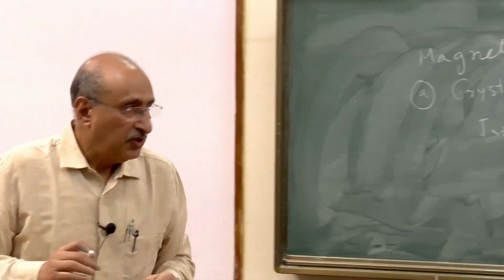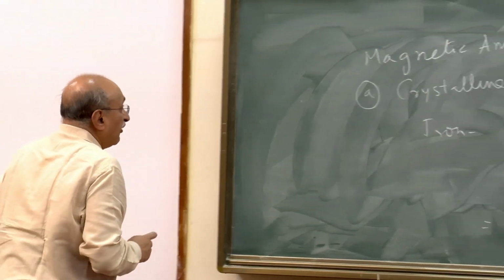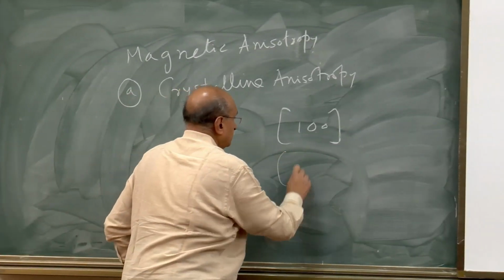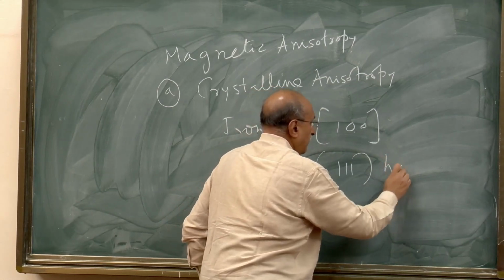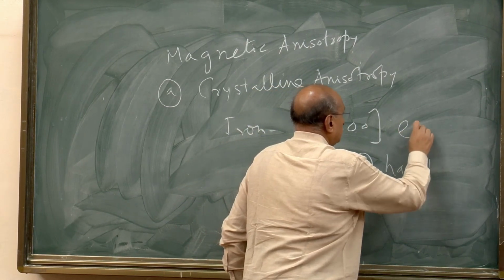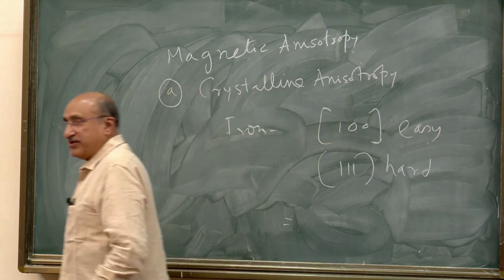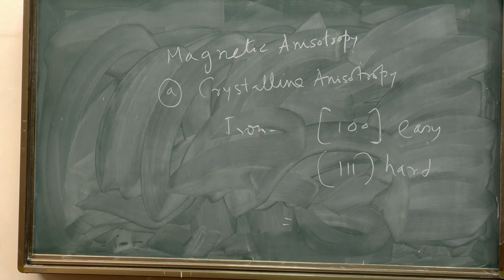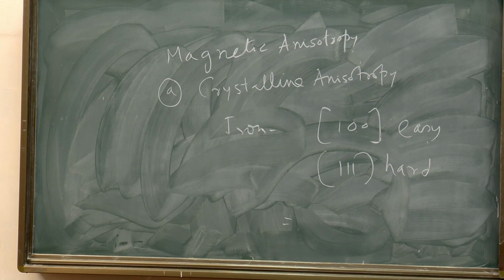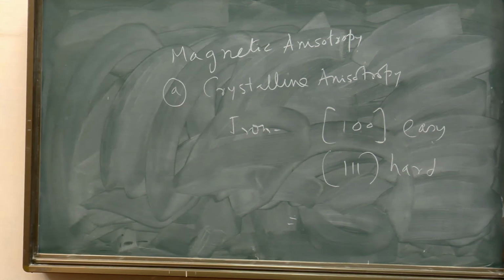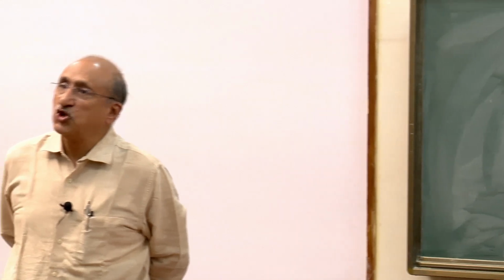So while 111 is the hard direction, it means if you want to magnetize iron along the 100 direction, it will magnetize quickly, with a very small field. But if you apply the field along 111, you have to keep on applying field until it overcomes that anisotropy and then magnetizes. Nickel is just opposite. 111 becomes easy and 100 becomes hard.